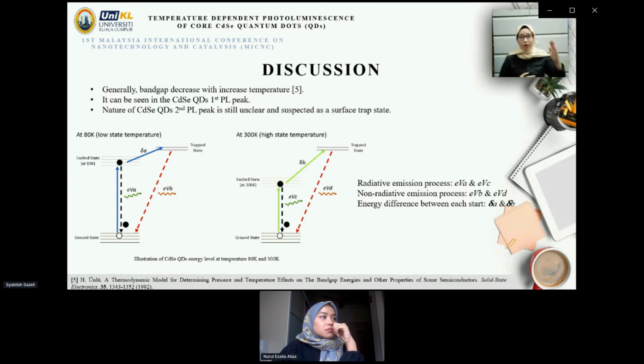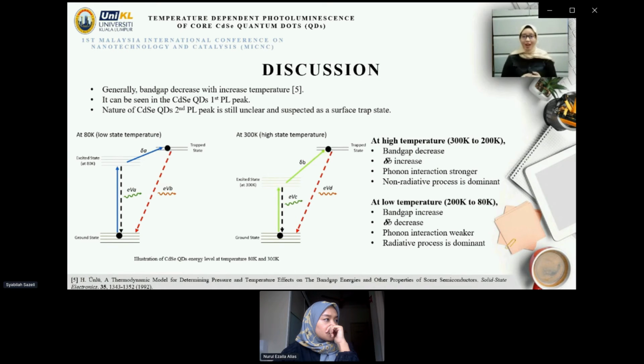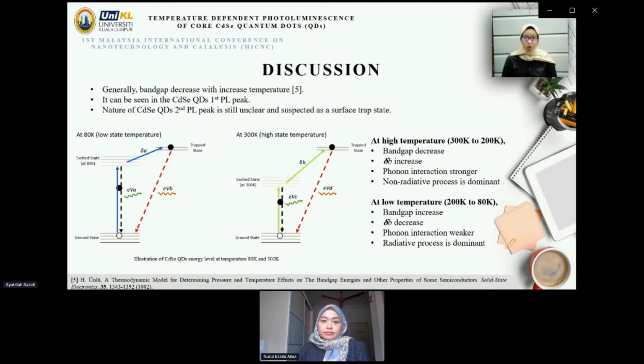As normally reported, PL intensity decreased as temperature increased. This is because the amplitude of atomic vibration increased and led to larger interatomic spacing. This behavior can be observed in the cadmium selenide quantum dot's first PLP, which decreased as temperature reached 300 K. But for the second PLP, the nature is still unclear. Thus, we suspect that it originated from the surface trap state.